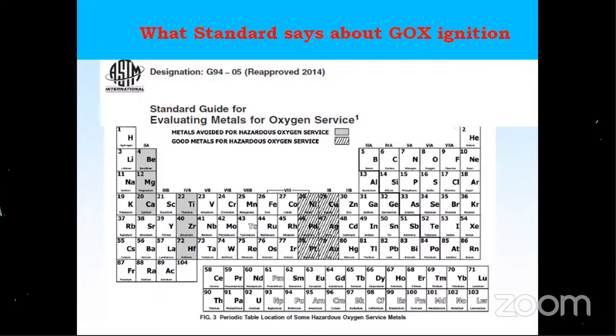What they have done is, wherever hot oxygen is coming, the entire area they coat with oxides. The entire oxygen path is coated with oxides. With that, they successfully made so many RD-170 and RD-180 engines. In fact, they are the only successful rocket engine people in the entire world to use oxidizer-rich staged combustion. So NASA wants to avoid this coating business, and they invested a lot of money to find out. I know one Dr. Monica, an employee of Boeing. For the last 15 years she has been working. She made an alloy, but unfortunately the forgeability of the alloy is so poor. So finally they made a powder of this alloy and, through 3D printing, made the turbopump and accessories, so that their engine is also ready.